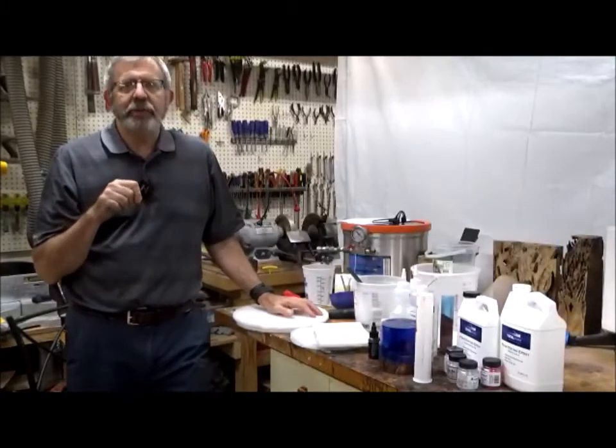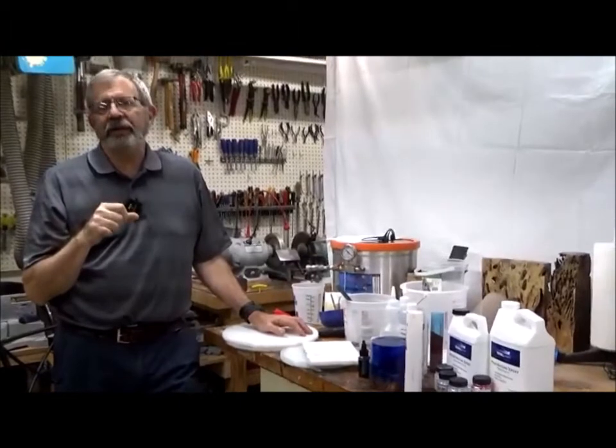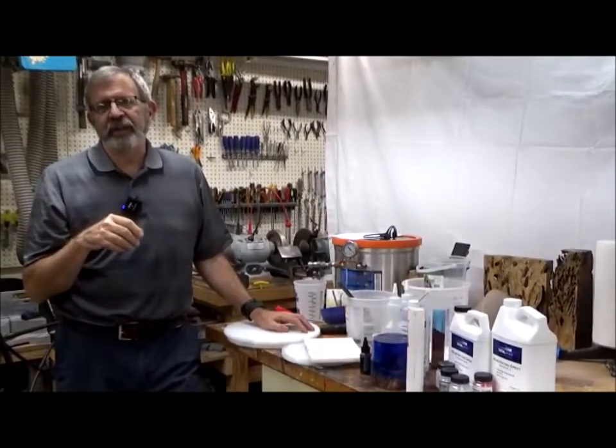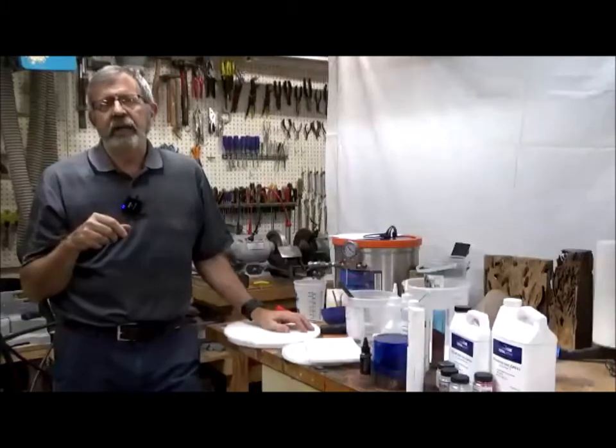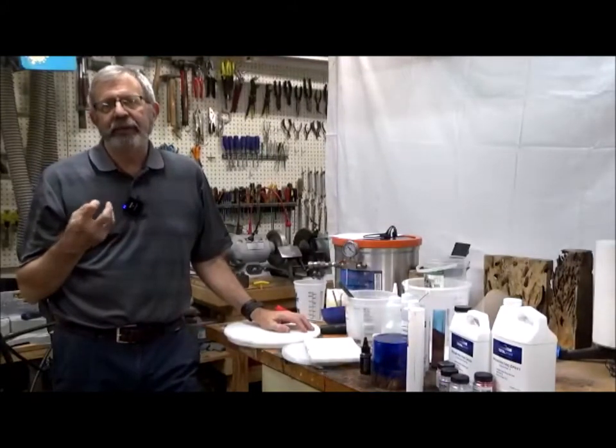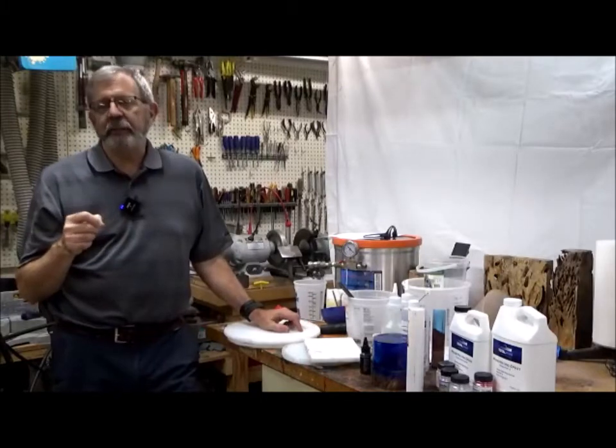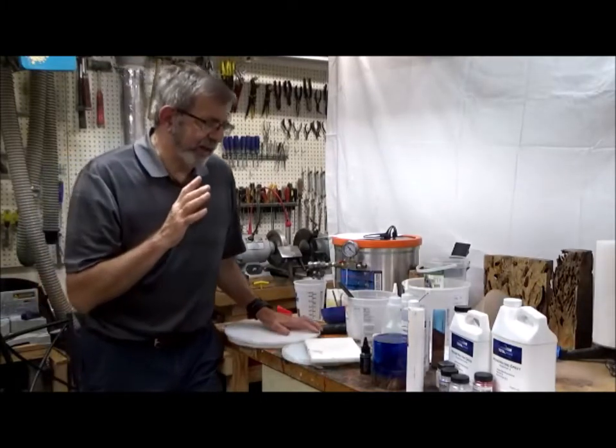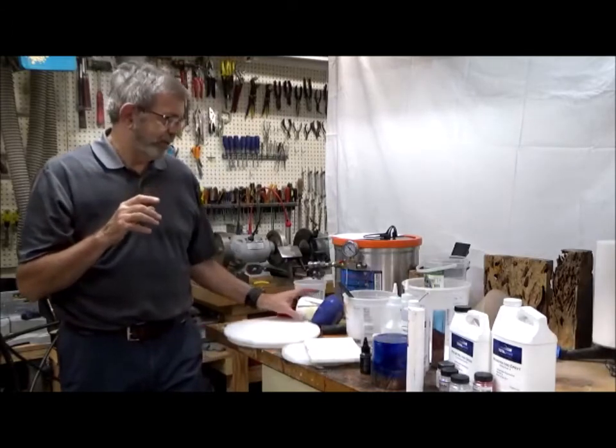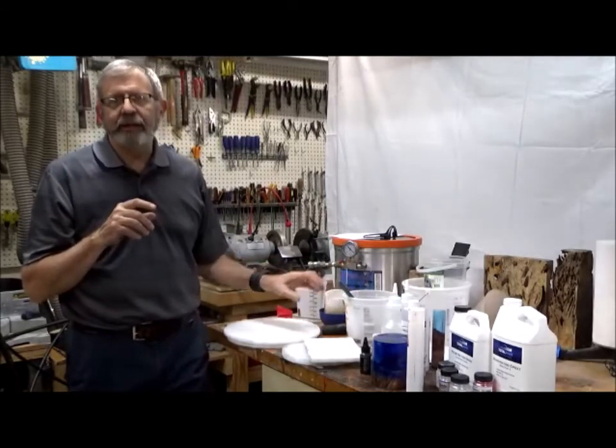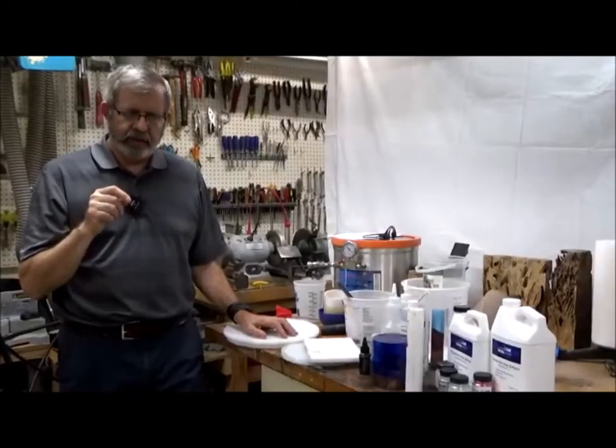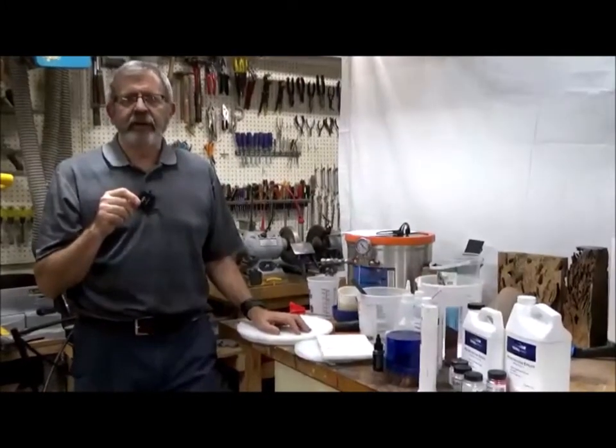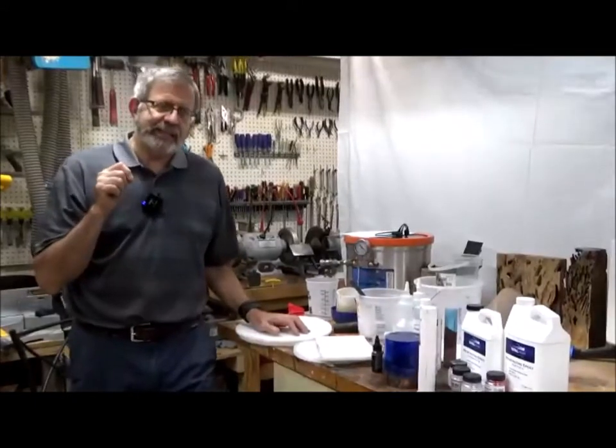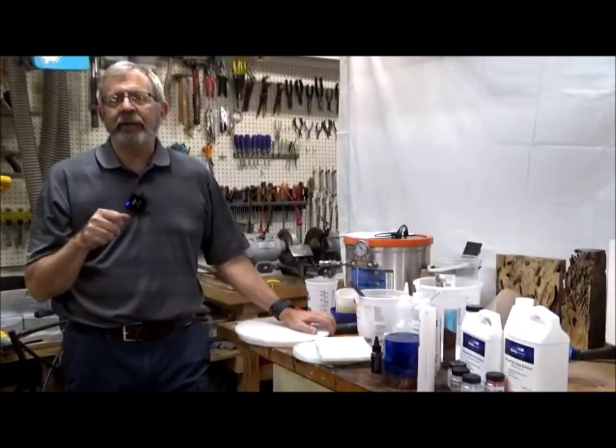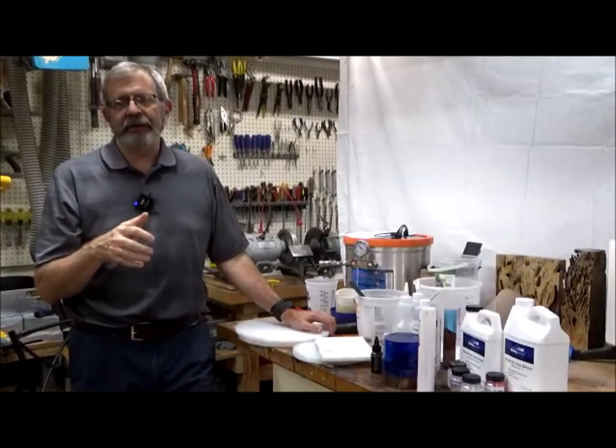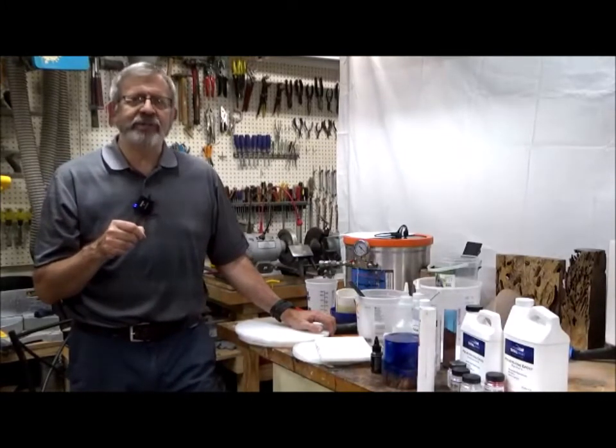It's a thermal reaction that's due to heat shrinkage. When it gets very hot and then it shrinks as it cools, that's what causes the cracking. I haven't had any that have pulled out. I forgot to mention, it is absolutely essential that if you're casting resins, the wood has to be very, very dry. So that's one of the reasons I tend to stabilize any wood that I'm going to cast resin against. I stabilize first, because I know it's dry. There's no moisture in there because all that moisture has been displaced.